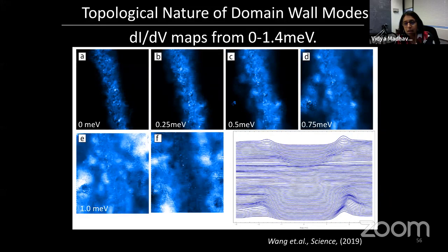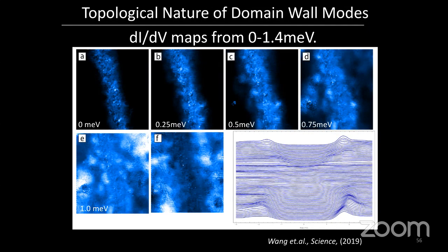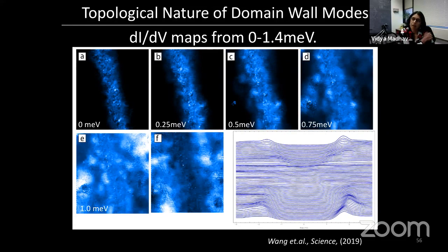We also did some calculations, which I didn't show here but are in our paper, for different kinds of situations, where you have just a simple superconductor without any topology, and what you expect to see at the boundary. Very often you get in-gap states, but those in-gap states can be anywhere inside the superconducting gap, and they're not necessarily spanning the superconducting gap, and they're certainly not necessarily at zero. So I agree, one should do more theory, but at least experimentally, there's a lot of evidence that this might not be a simple destruction.